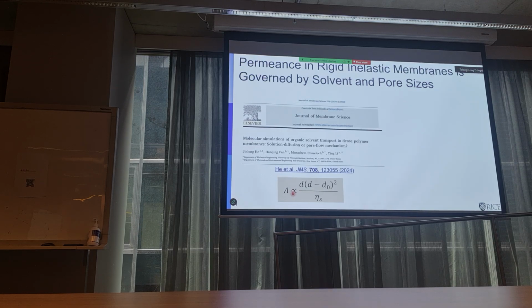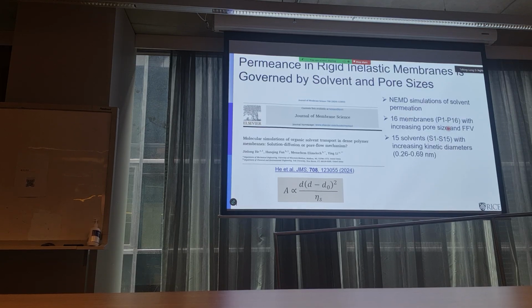And later we did molecular simulation with, again, Ingli, who is an expert on molecular simulations. And in this paper, we also tested if this equation is also valid when we get these molecular simulation fluxes. We did non-equilibrium MD simulations of 16 different membranes with different pore sizes, fractional free volumes, and different polymers. And then 15 different solvents of all sizes, with kinetic diameter from 0.26 to 0.69. And we got very good correlation to this equation. And more importantly, we found that if the solvent is larger than the pore size, it will not go through the membrane.